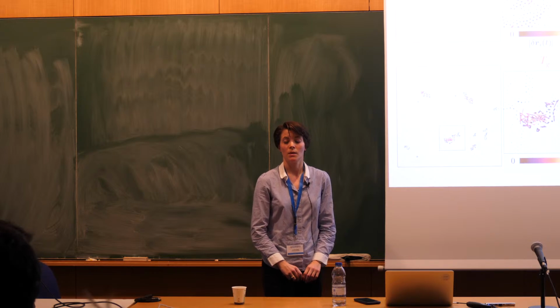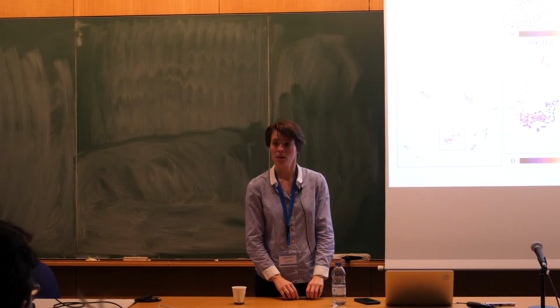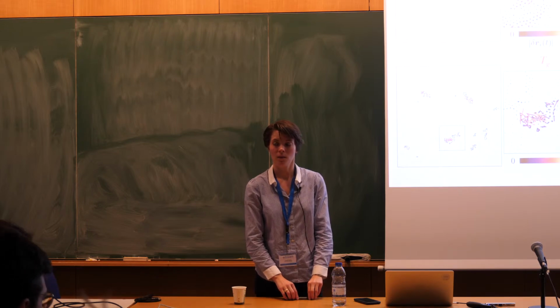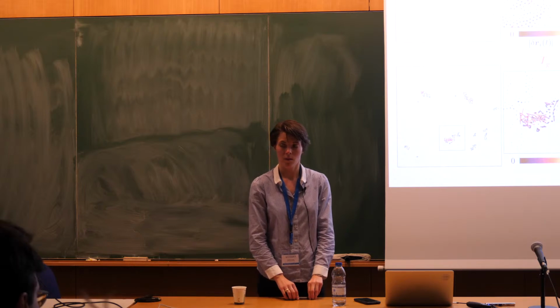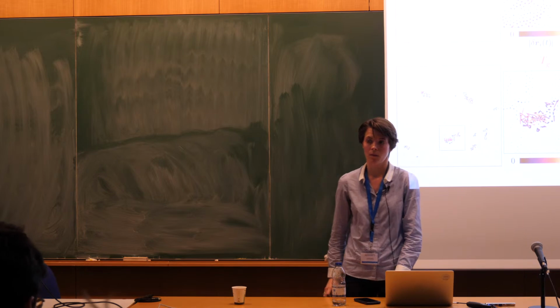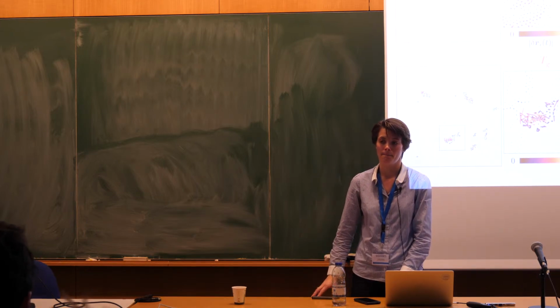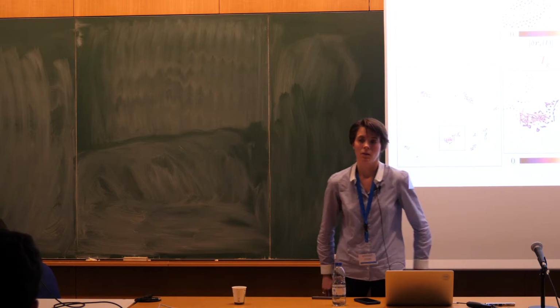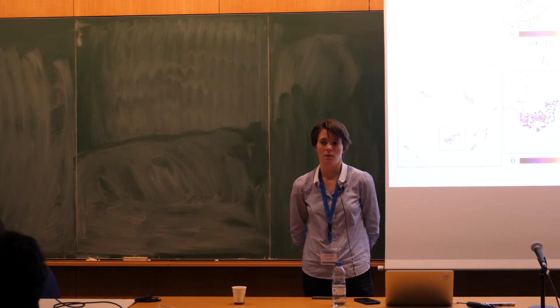We actually did this kind of study in the grain case, and there, when increasing the packing fraction, we could notice that in this vibrated grain system, we are in the regime where it's not soft spots anymore, it's more the kind of clusters that you see. But then when we were increasing the packing fraction further, these initial clusters were getting larger, and so to relax the same fraction of the system, you needed less facilitated events because you had already done a lot with the very first excitation. So although facilitation was still the dominant dynamics that would lead to the total relaxation of the system, a larger fraction of the system was already relaxed from the very first events.